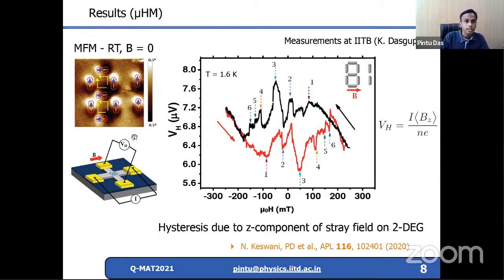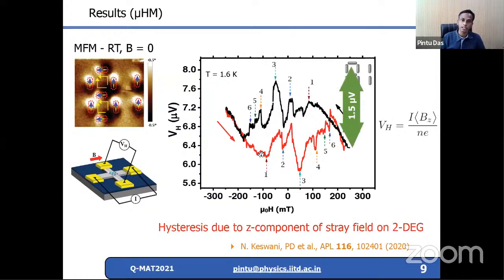So what you see here is the MFM image of the 9 nanomagnets that I have shown, and these are the Hall voltage, actually, if you remove the background. So this is the Hall voltage that you measure. We see a very nice hysteresis loop, and on top of the hysteresis loop you see very rich features, which obviously you don't see in the global measurements. These are the stray field which we have measured, and in the Hall voltage, the entire signal is just less than 1.5 microvolt.